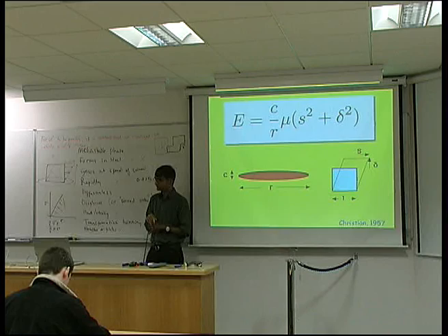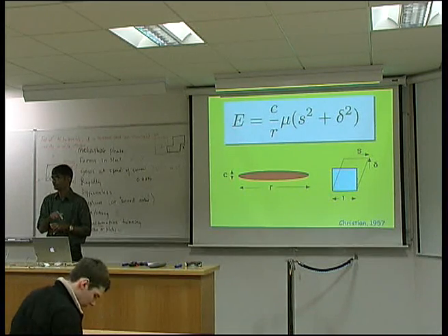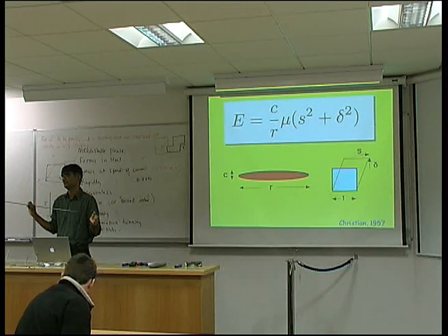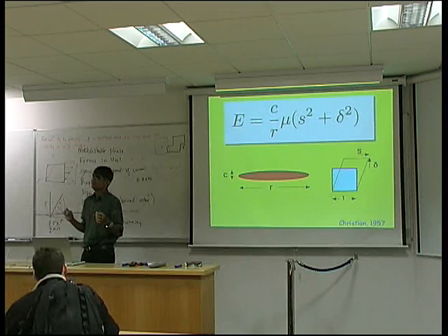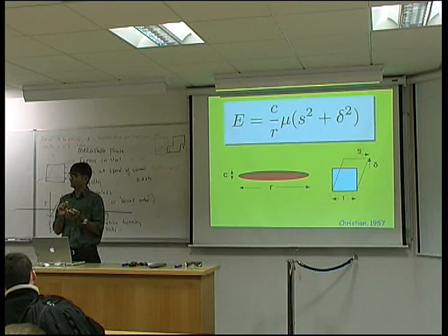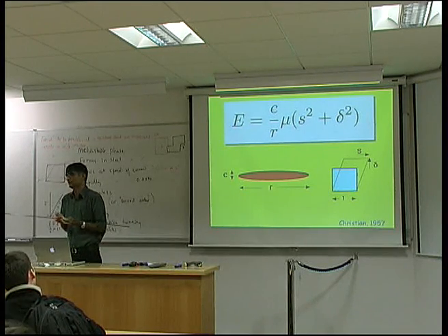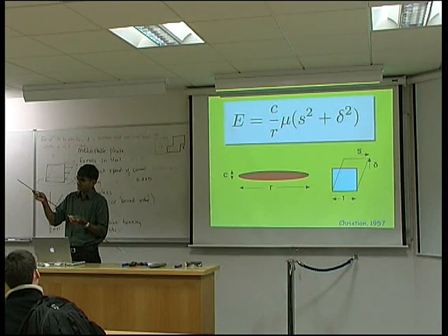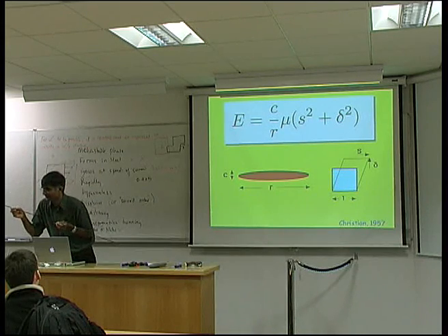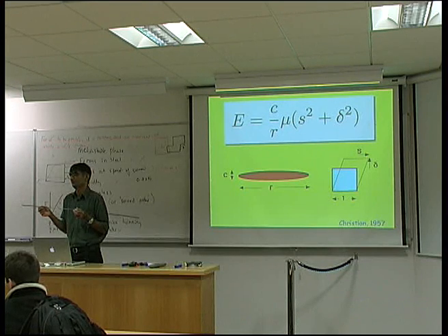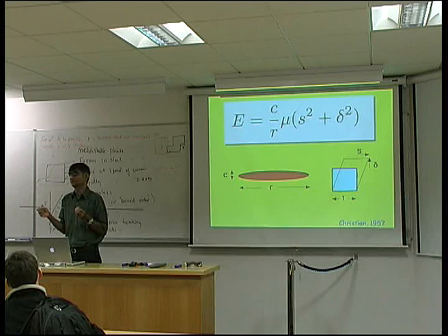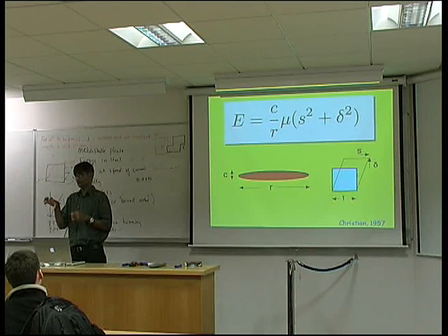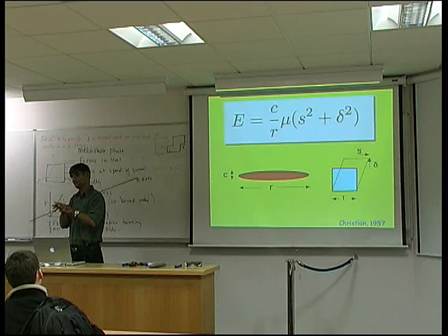No, the invariant line is also irrational. I haven't mentioned that, but we will do that in the next lecture. It can be an irrational line which is perfectly coherent. You see, it doesn't make sense to talk about a 3, 10, 15 plane where we have planes of atoms. But if you make steps between planes, then the average plane can be 3, 10, 15. Similarly, the average line can be an irrational line. Yeah? As for the invariant line, you cannot talk about it being in the original crystal, because you have to have two crystals to define the invariant line. Right.